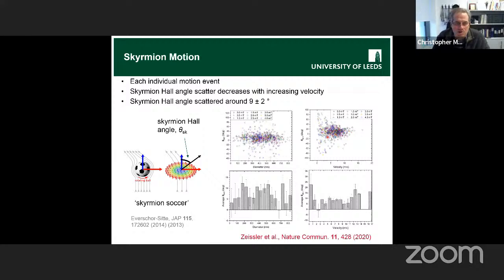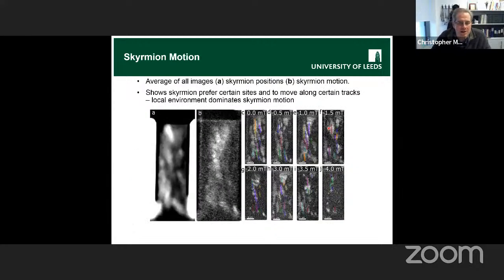So we can sort of see that energy landscape if we just take all of our images and add them together. So that's what we've done on the left here. And what you can see is that this is not uniformly grey at all. There are some bright patches and streaks separated by dark regions. And so these bright areas are where we are very likely to have seen a Skyrmion. And they will sort of move down. There are sort of roadways that they follow through the material.